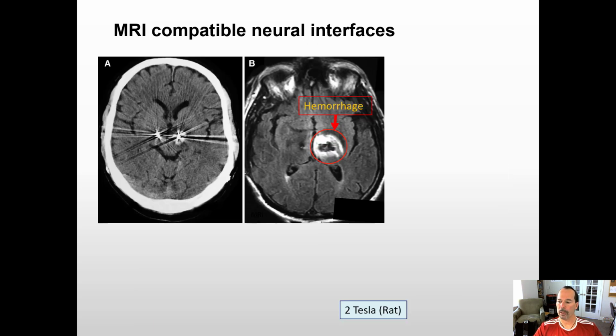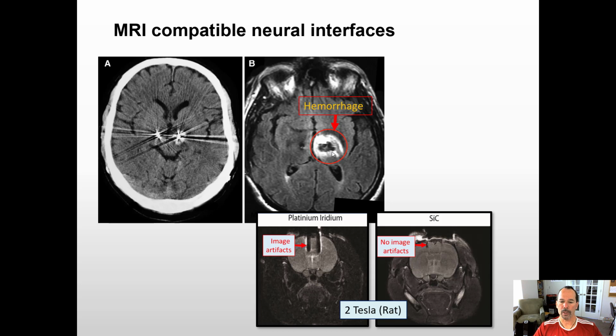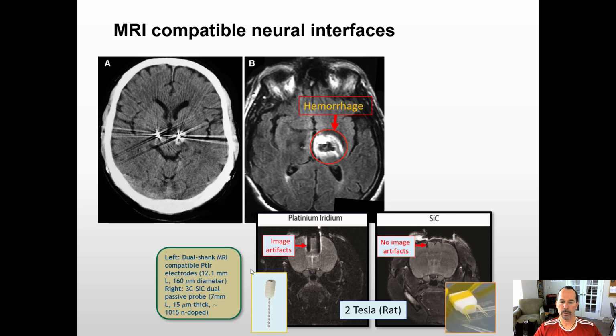So the last topic I want to discuss, we're running out of time, is the issue of MRI compatibility. Here we see some MRI data showing damage caused by implants in the brain. In 2012, while I was on a Science Without Borders project in Brazil for this topic, we put some devices in rat brain at 2 Tesla, and we saw a large amount of image artifacts from the so-called platinum iridium MRI compatible device, which you can see here they've twisted the wire to try to reduce the coupling, whereas our bare silicon carbide showed no artifacts whatsoever.